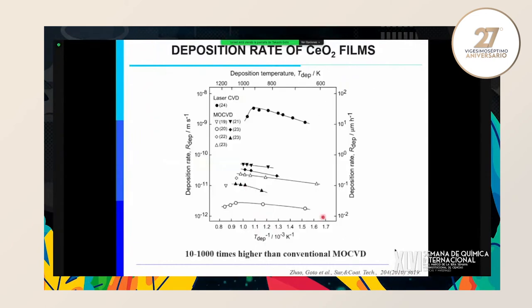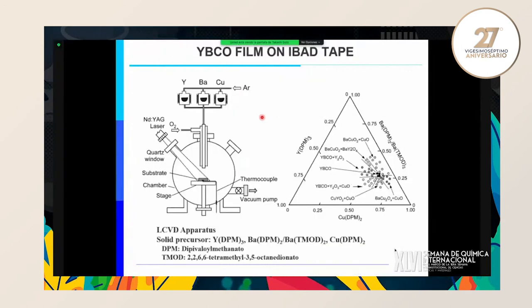The deposition rate of ceria is also very high, around 100 to 1000 times higher, because there is less nanoparticle formation in the gas phase. Then we can deposit YBCO film on ceria-coated IBAD tape.